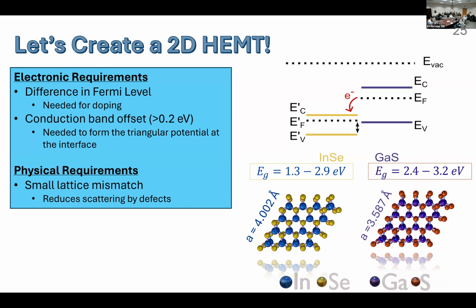Question. Yes. You have quite a range of band gaps with all these materials here. What is the origin of that? Quantum confinement effects. So this is thickness dependence. Yes. So this range is for as you go from bulk to monolayer. So for bulk values, you have typically smaller band gap values. But as you go to the monolayer form, quantum confinement effects increase this value.